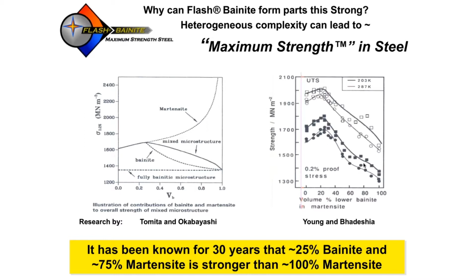Now, what's really exciting here to see is that around 20 to 25% bainite in a martensite matrix, you can actually get the steel to add another 100 megapascals of strength from the exact same alloy of steel. So that's kind of interesting. So your steel cost shouldn't go up, but how do you achieve this? So this has been known for, gosh, over 30 years that this mixture can make steel stronger. Well, 10% stronger might not sound like a lot, but 10% thinner starts to add up really, really quickly when you start talking about all the steel in a passenger vehicle or an armored vehicle.